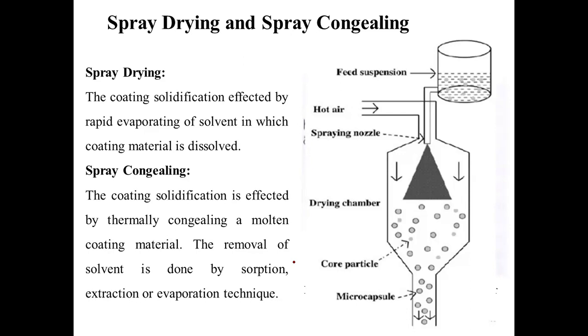In modern spray dryers, the viscosity of the solutions to be sprayed can be as high as 300 millipascal seconds. Spray drying and spray congealing are similar processes, in that both involve dispersing the core materials in a liquefied coating substance and spraying or introducing the core-coating material mixture into environmental conditions where rapid solidification of the coating is formed. So these are the two methods, spray drying and spray congealing.